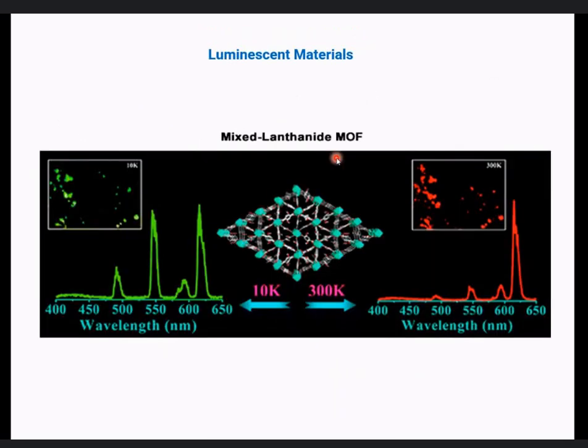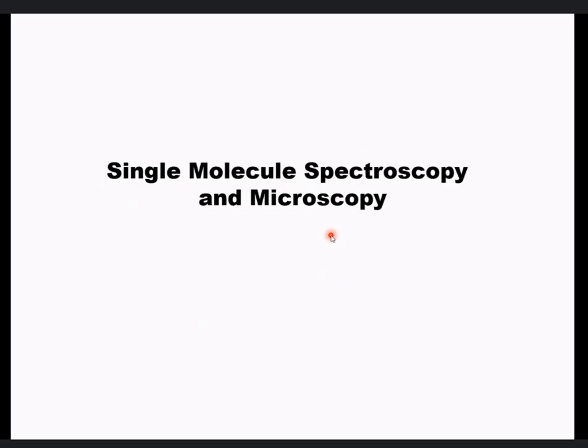Apart from that, these are very much luminescent materials. As I mentioned, if you have a hybrid complex with metals like lanthanides and transition metals and form the MOF, then they can emit light in the green, depending on the material, lanthanides, terbium or europium, or maybe neodymium in the near IR region. So they are very good luminescent materials useful for LED or other preparation. Again, MOFs may be used as an imaging technique, provided they are biocompatible.